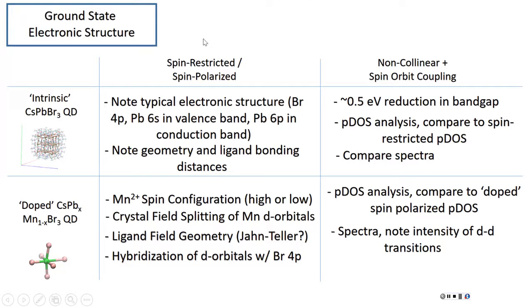So then for spin polarized calculations for the doped system, there's a lot going on there, because first you have to figure out whether it takes a high or low spin configuration, because those are kind of the two favorable for Mn2+ in a ligand field. And halides generally give a high spin configuration, so 5 spin up electrons, which is what we found was the lowest total energy of the system. And that kind of follows what's been reported in literature when they look at these things experimentally.